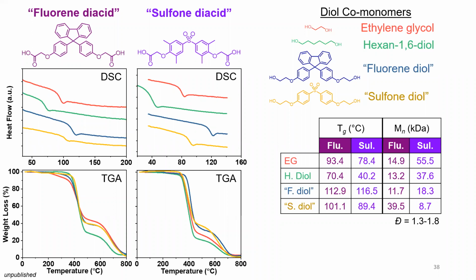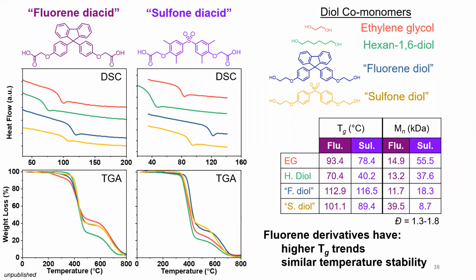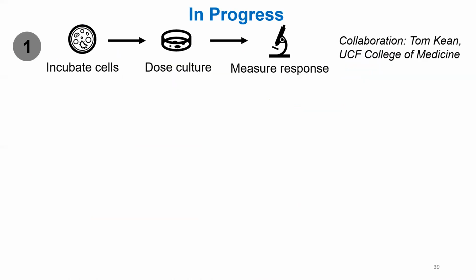And it looks like the sulfone is much more stable because of this change here, but I think statistically, really, they're quite similar. So I will just say that the fluorene derivatives have higher Tg trends, but thermally, they're pretty similar in their stability. And this is step growth polymerization, so we expect to have dispersity closer to 2, and some of the lower dispersity is not because I discovered something new. It's that there are lower molecular weight materials. So if we do longer polymerizations, we'll definitely see that PDI increase.